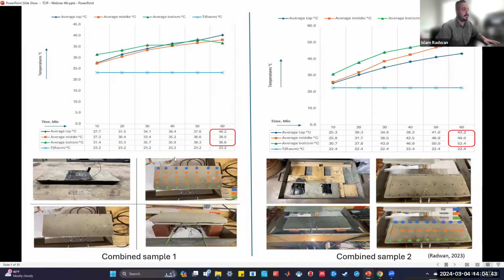For the combined sample one, as we can see here, the difference between the surface temperature, the original one, which is 23 Celsius, and after 60 minutes, we can see the difference. So the averages for the top and the middle and the bottom, it's 40 Celsius, 38, and 36. The same thing for the combined sample two.